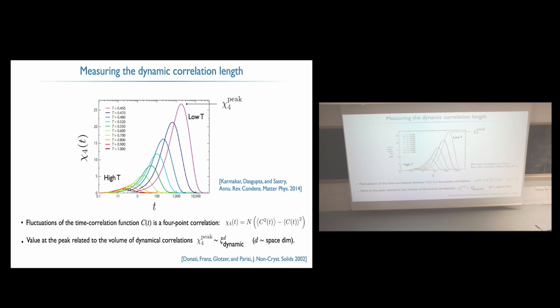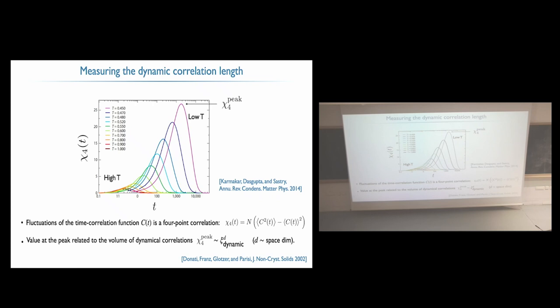But as you cool the system, you see that the peak, which basically corresponds to this tau alpha, here it peaks around tau alpha, you see that it shifts to the right, which is the system just slowing down. But you see that in addition, you have the peak that grows in size. And actually, you might accept this for now, but the peak value corresponds to the volume over which the dynamics is correlated. So I was showing you just before, this dynamic length scale, basically the value of the peak tells you how large these domains are. So you see that as you decrease the temperature, you really have this length scale that increases for the dynamics.